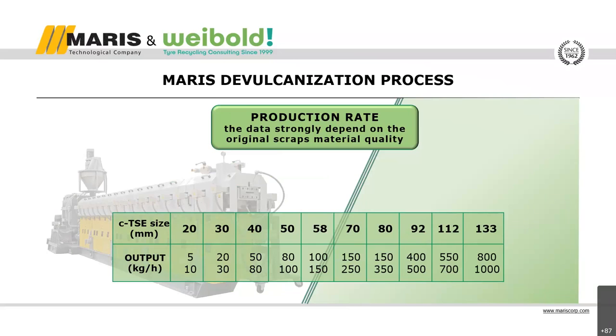For a medium or a pre-industrial scale, that means 50 or 58, we can produce 80 to 150 kg per hour. And for big production, we can reach 1,000 kg per hour with our 133 millimeter.